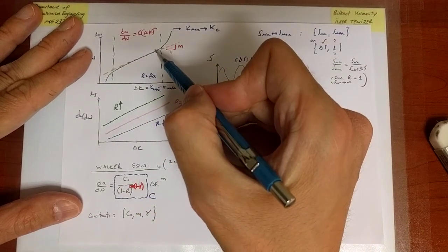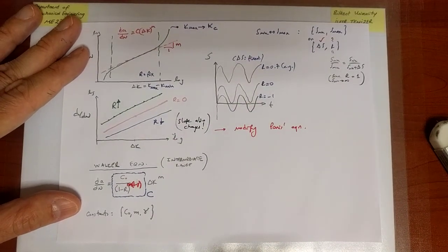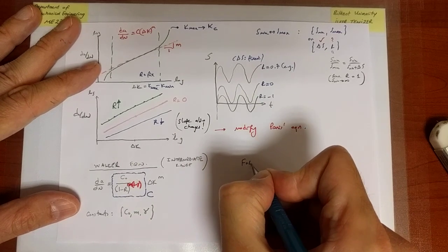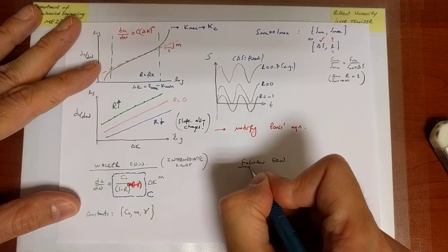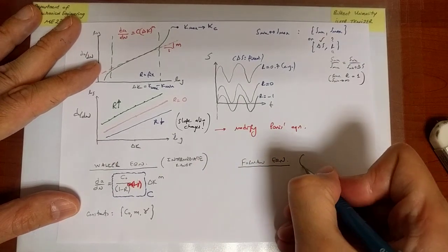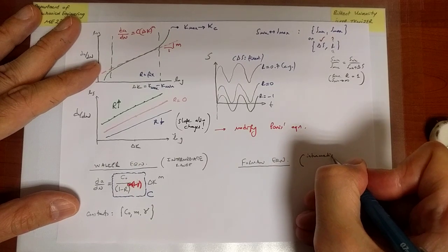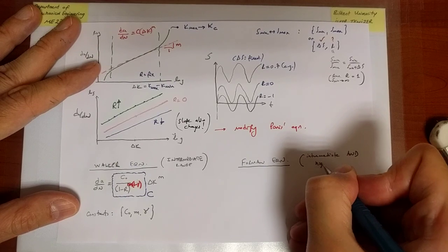That's not going to happen. The line should curve up and give an increasingly higher crack growth rate. And that is the goal of the Forman equation. The Forman equation is a crack growth model that works all the way up into the high range. So it's intermediate and high range.